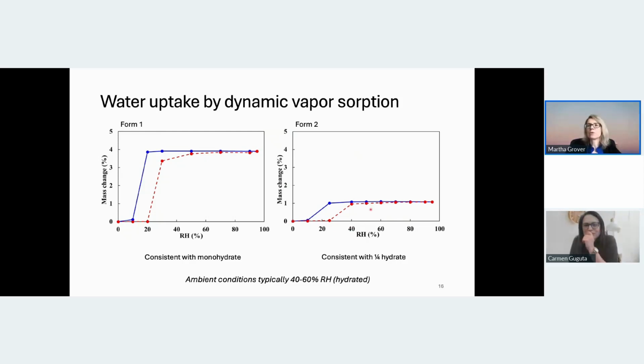We needed to reconcile the difference in conditions after we did the DVS, and then we realized we would be on opposite sides of the hydrated-dehydrated transition. But regardless, I think what we conclude is that this is a small amount of water uptake that is not leading to a structural transition in the compound's crystalline structure. It could simply be on the surface. It might not always be 1%, depending on how much surface we have.